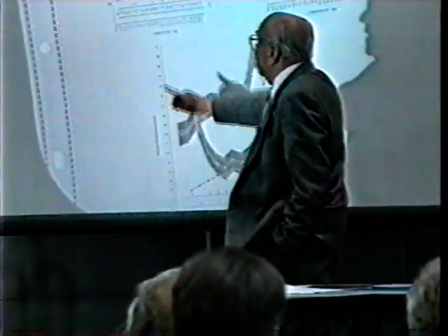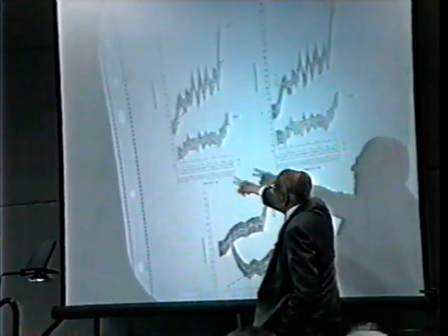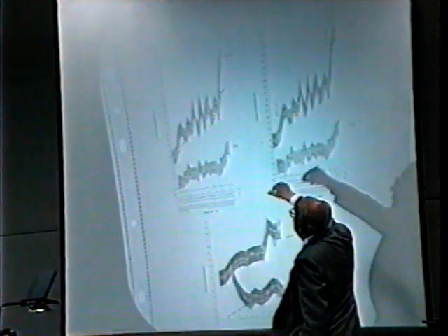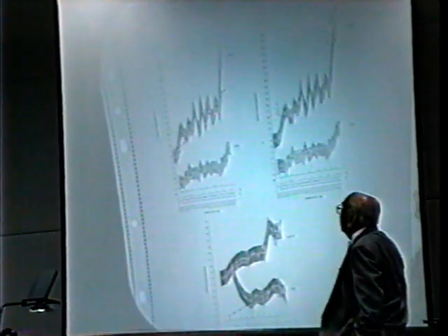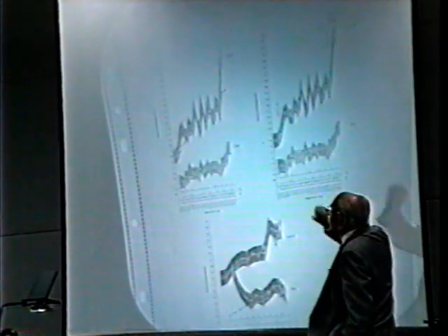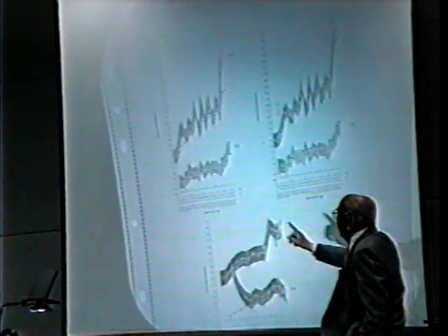You can see clearly that there is a production in I think second or third day, and then we didn't see anything until toward the end when we terminated. It was quite high. You can see also that the tritium was detected in the liquid phase, not in the gas phase.